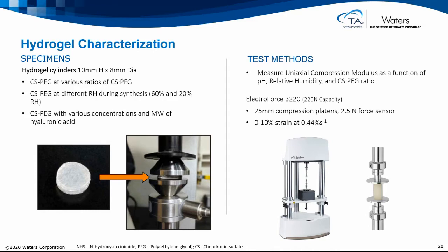From a methodology perspective, they're using one of our ElectroForce 3220 instruments, 225 Newton capacity, and they're going to measure a compression force by applying a compression strain, like an increasing strain from 0 to 10% strain. You can see the strain rate. And they're doing this between platens. Some people call those parallel plates. And a little bit of an element here that's interesting is a 2.5 Newton force sensor. So this is a 225 Newton capacity instrument, but if this material will only yield, let's say, less than 1 Newton of force when you do this compression, it's helpful sometimes to put in a lower capacity force sensor. It basically boosts the signal, giving you more resolution in measuring the compression force, with more accuracy and more precision.